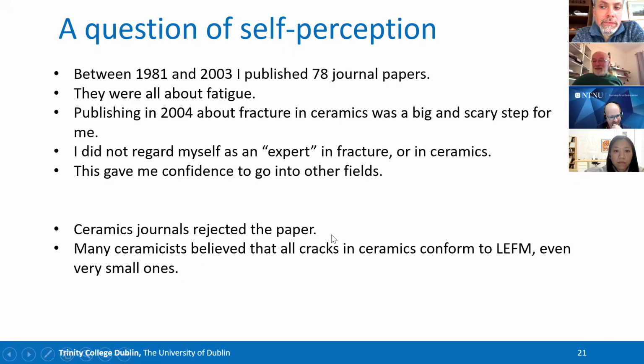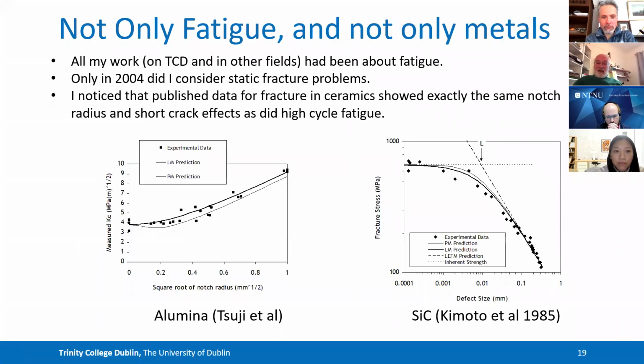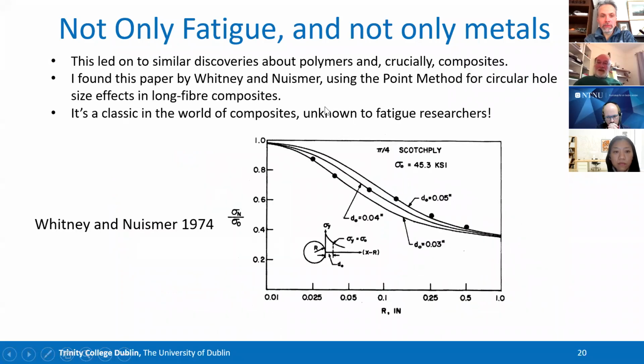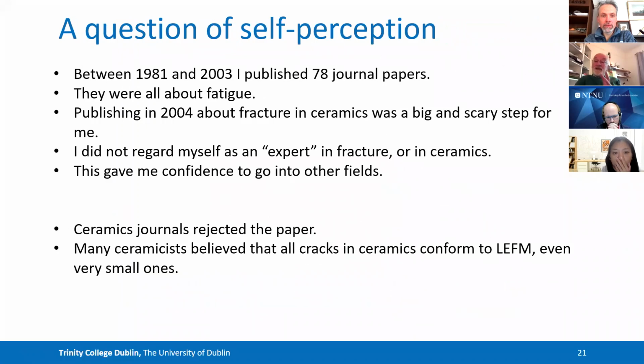And again, this was a paper I found quite difficult to publish. At the time, I'm not sure if it's still true, but at the time, the prevailing view amongst ceramics people in relation to fracture was that all cracks in ceramics are Griffith cracks, as they would say. All cracks conform to LEFM. And there's no such thing as a small crack in the way we think of it in fatigue. So what I was saying was different from that. I was saying, going back to this graph, look, these small cracks here, some of them are so small that they don't affect the strength. Others don't conform to LEFM. You have to get above a critical crack size before they conform to LEFM. And many reviewers in those journals just wouldn't accept that idea, because it seemed to be a fundamental tenet for them. So I think I published that one in Engineering Fracture Mechanics, eventually, one of the fracture mechanics journals.